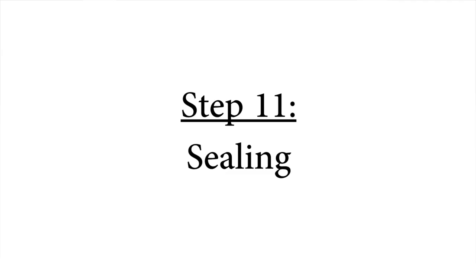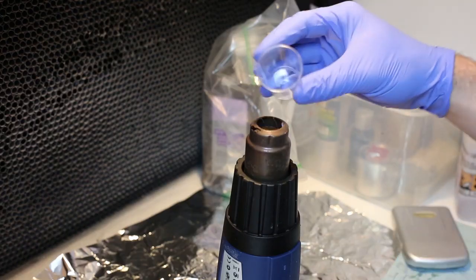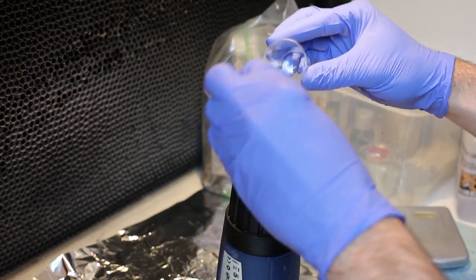Step 11. Sealing. The hologram has to be sealed, so the emulsion is protected from outside moisture. DCG is very hygroscopic and sucks the humidity right out of the air. This causes the emulsion to swell, which collapses the fringe structure and makes the hologram invisible. It can be made visible again by redeveloping the plate, but by properly sealing it in the first place, this is not necessary. First, I prepare the tools that I will need for sealing.